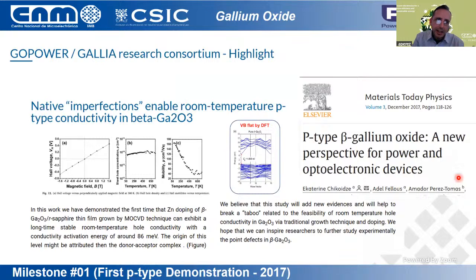Here are what I mentioned before, which was that the theoretical predictions are that there is no option for hole conduction in gallium oxide because the valence band is flat. We demonstrated that this is not the case, and gallium oxide can have perfectly free holes in the material. So that opens the door to make any kind of device like in silicon or silicon carbide, so MOSFETs or IGBTs.